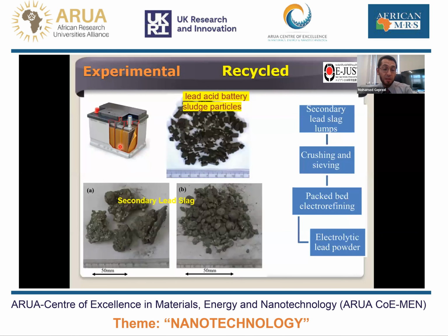The lead acid battery is used everywhere, with very high consumption. We use different ways to recycle lead acid batteries. You can use the sludge directly and do electrolysis, or remelt by pyrometallurgy, and the secondary lead slag of the process is what doesn't go directly by pyrometallurgy. So we reuse the lead, and the lead oxide that has gone to the slag is recycled. They crush it and do electro-refining, and then we have electrolytic lead powder at the end.